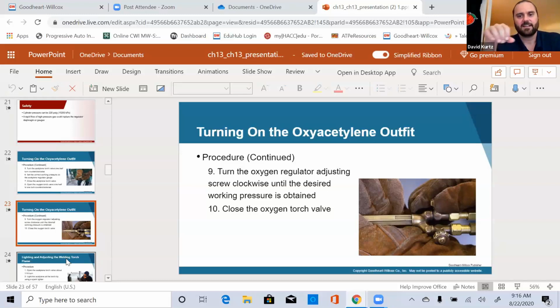Once that's set, I open my needle valves to check how much drift I have on my regulator. If I'm at 3 PSI and it drifts down to 2, I shut my needle valve back off. I know that it's going to drop 1 PSI. So I open my needle valve back up. It drops to 2. I tighten my adjusting screw so it raises the pressure to 3, shut my needle valve off. The book says to just open your needle valve and adjust your screw.